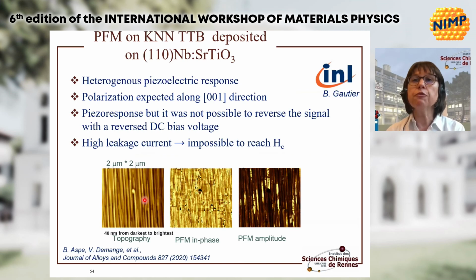For characterization, first, PFM has been performed in INL by Brice Gauthier on such films deposited on 110 niobium-doped strontium titanate, and a heterogeneous piezoelectric signal has been observed. So the film is piezoelectric, but it has not been possible to switch and reverse the domains because of leakage current that makes it impossible to reach the coercive field.